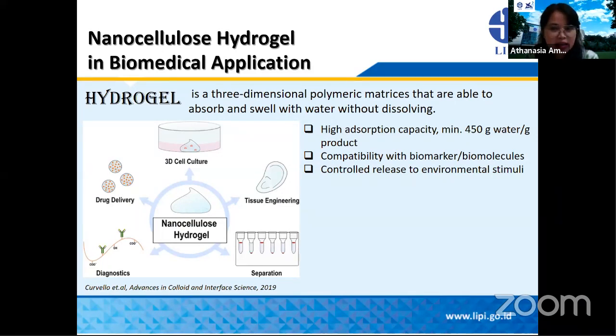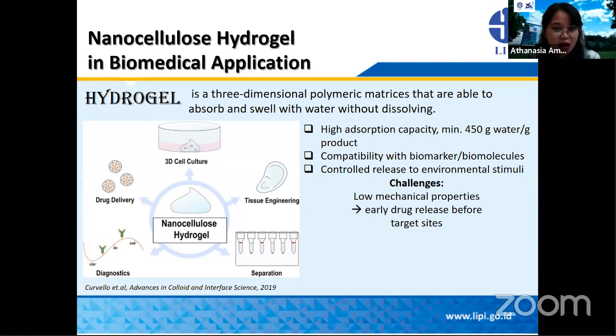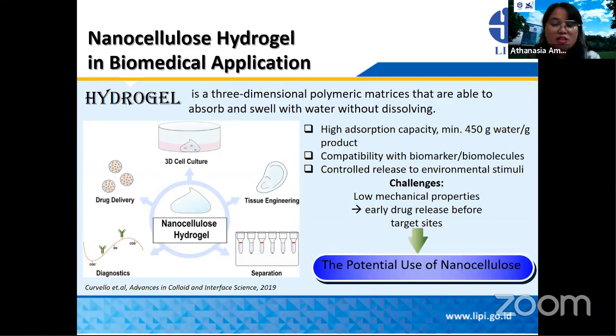The second one is compatibility with the biomarker, because for biomedical use we usually introduce living biology into the hydrogel system. And the third one is controlled release, which is very important and can be managed by using environmental stimuli. However, there are challenges in developing hydrogels for biomedical application. The most important challenge is the low mechanical properties. This can give a problem, especially it can induce early drug release before reaching the target site. To address this challenge, we can use nanocellulose to enhance the mechanical properties.